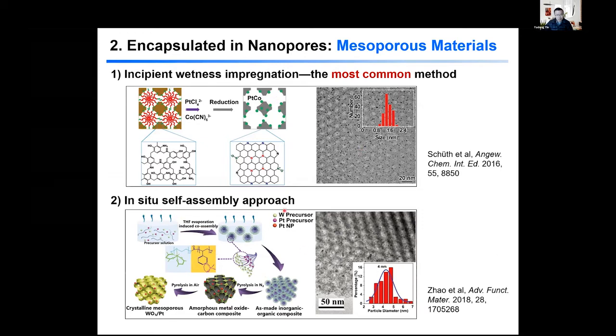And there's also in-situ self-assembly approach, and you can introduce metal cations onto the block copolymer, and then self-assemble block copolymer into superstructures like spherical particles, and then evaporate solvent, and you organize them into three-dimensional ordered structures. After pyrolysis, you actually convert this block copolymer into carbon network, and in this case you have mesoporous carbon with oxide inside with platinum nanoparticles there. You can go further, you can pyrolyze in air, and then you can get rid of the carbon, and you end up with platinum nanoparticles inside tungsten oxide, for example, in this case, framework. And as you can see, the size of particles can be very small. They are very stable within the framework.